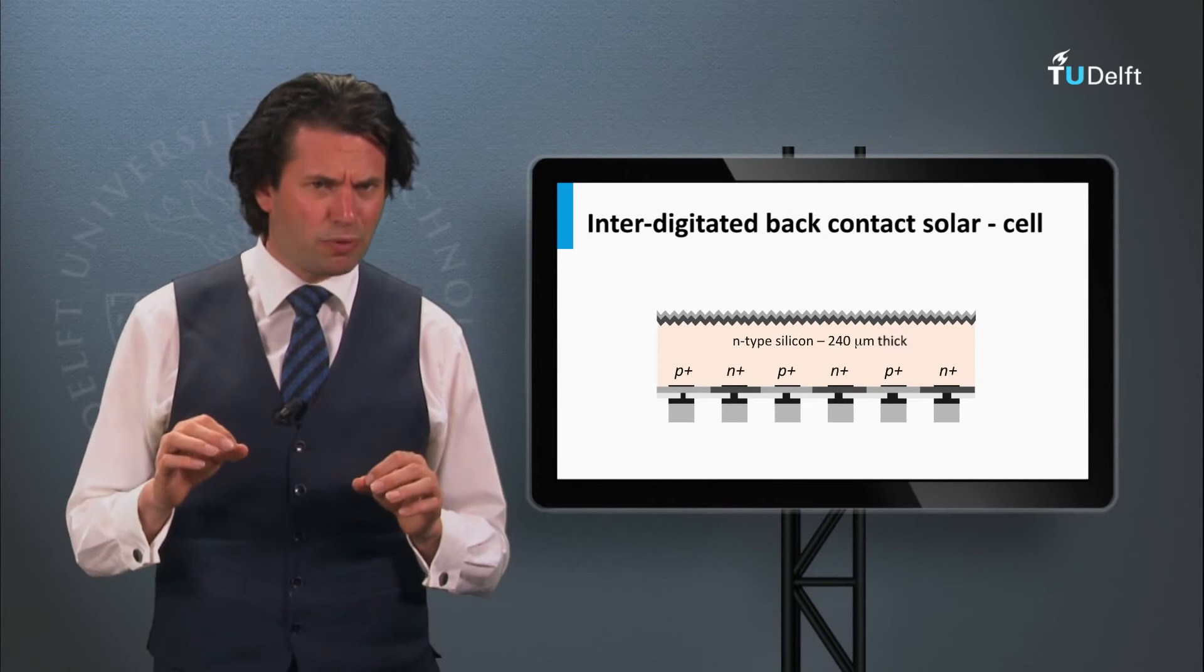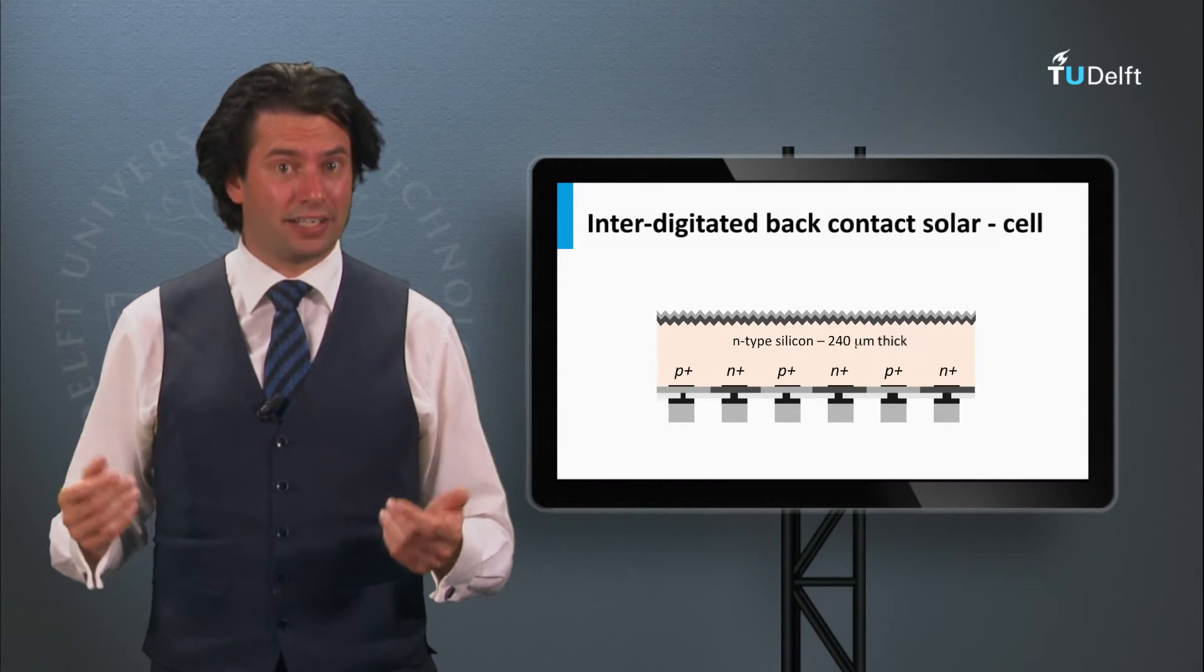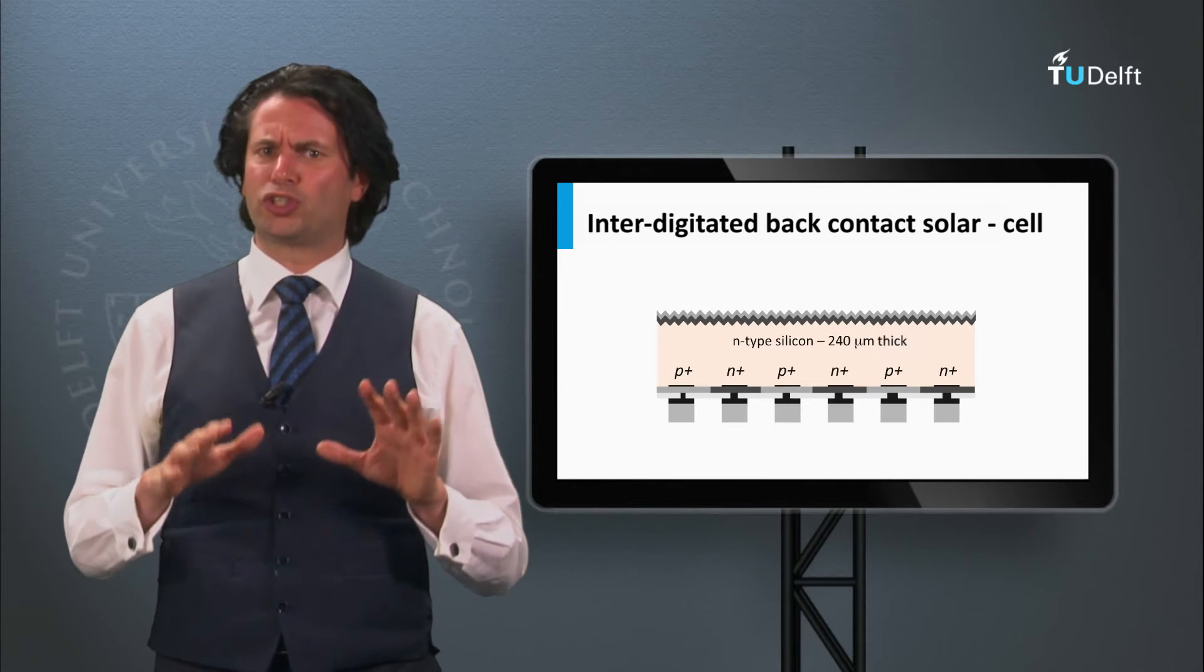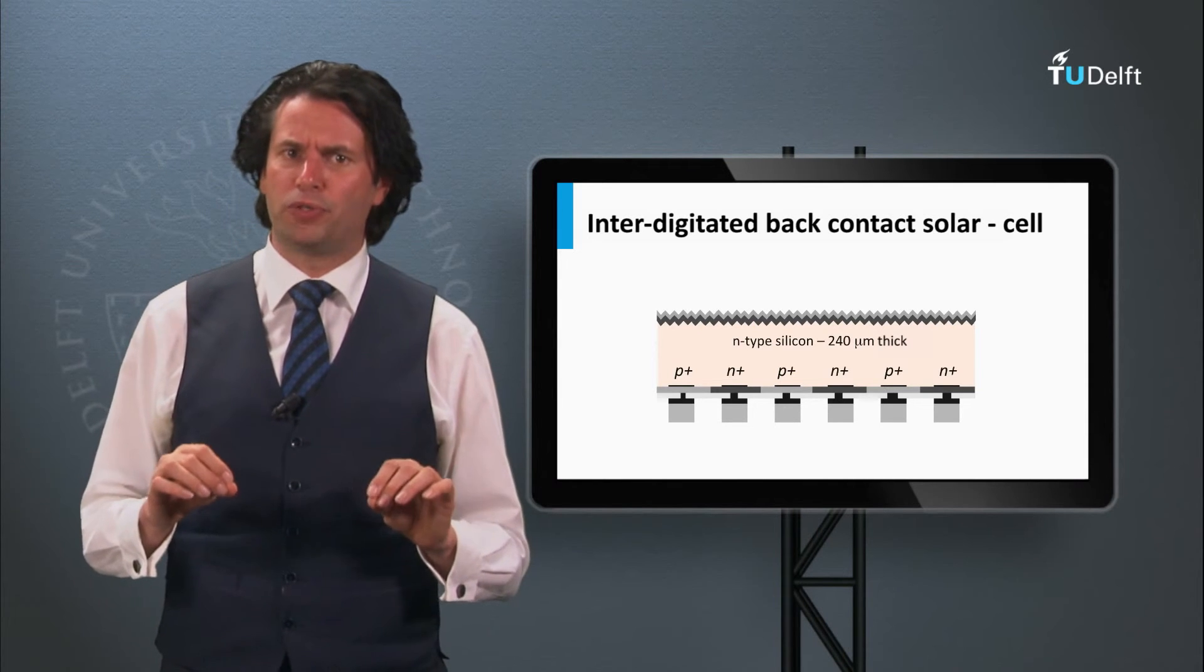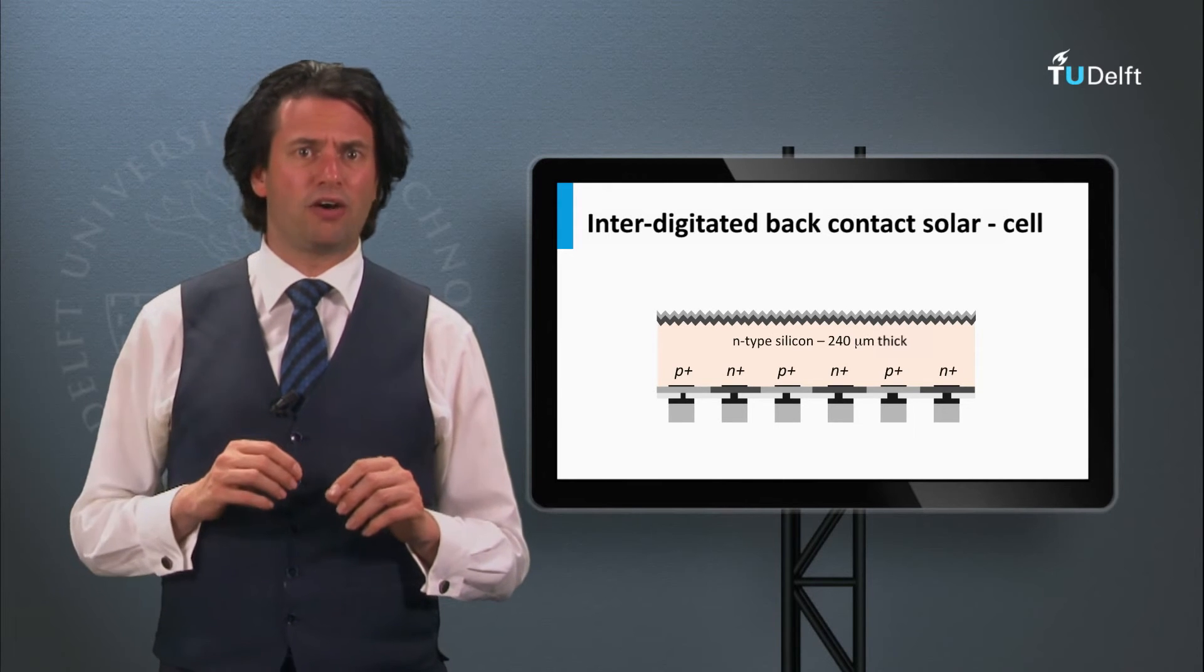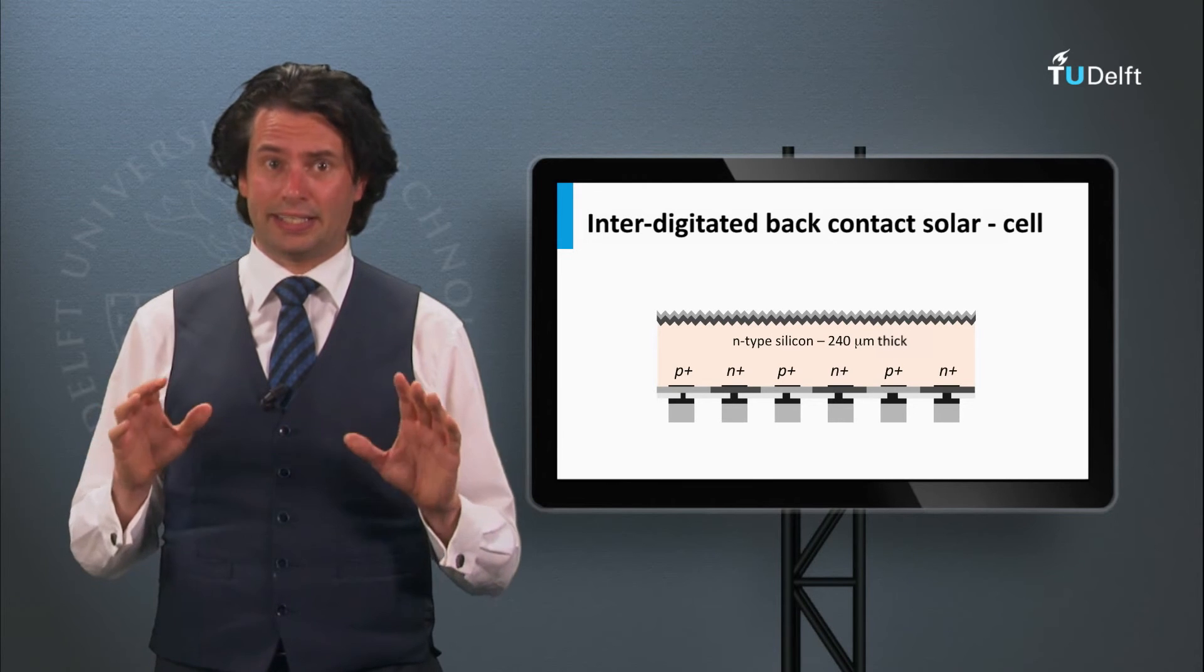which under light exposure start to make complexes that act like defects. The light-induced degradation causes a reduction of the power output with 2-3% after the first week of installation. This effect is not present in N-type wafers.